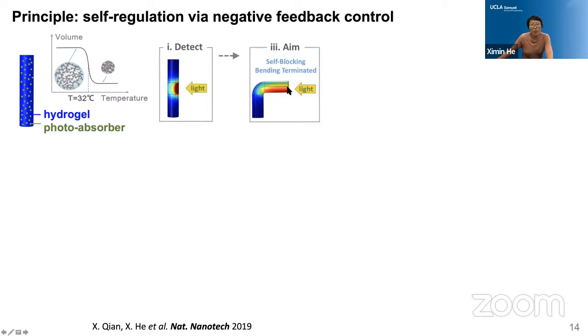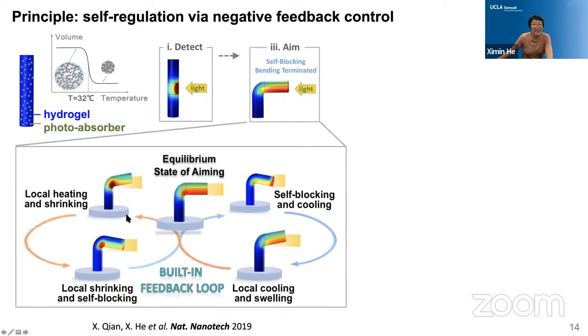And as soon as this pillar bends over to be close to aligned or aiming to the light, then this is a critical moment. We hope the pillar knows this is a place to stop. And then indeed, we found the pillar, due to this light material interaction, creates an interesting built-in feedback loop. So when the pillar bends over, the tip will block the light from shining onto this hinge area. So this area will cool down and reswell and make the tip lift up again. So this will allow the light to shine back on this hinge area for the tip to bend over, right? So these overbending and underbending configurations will compete with each other to make this pillar tip point to the light steadily.